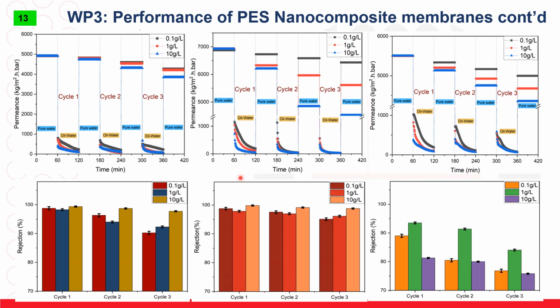And we also performed a chemical oxygen demand analysis to check for the carbon content in the feed as well as permeate solutions. And as can be observed, the rejection performance was very good for the hydrophilic membrane, and it was very poor for the hydrophobic membrane. This can be linked to the relationship between hydrophobicity and oleophilicity, the love for oil. When the membrane is hydrophobic, it is oleophilic, which means it is easy for oil to cross through such a membrane, which was not the case for the hydrophilic membrane,